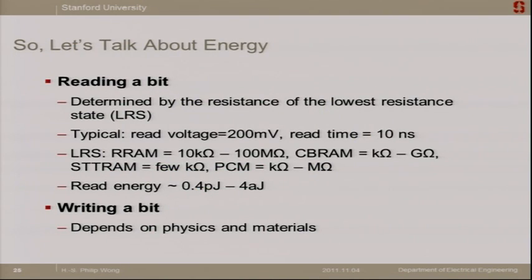All right, so let's talk about energy. The read energy of the memory is really determined by the resistance of the lowest resistance state, the LRS. Let's say you have a pre-charged bit line, and you have a typical read voltage of 200 millivolts, which is typical. Say you have a read time of 10 nanoseconds.